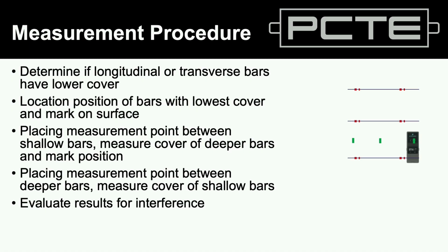On a profometer, that's the crosshair which lights up and indicates the position of the bars. There's also some lines on either side showing the midpoint of that. We move that measurement point through the middle of the reinforcing bars. By doing that, we've reduced as much as possible the interference. And if these bars are spaced more than 150 millimeters apart, that's all we need to do. We've got a good number there, and we can go in and out and check the bars in the other direction and see if they're a bit closer to the surface. At that point, I've got good numbers.